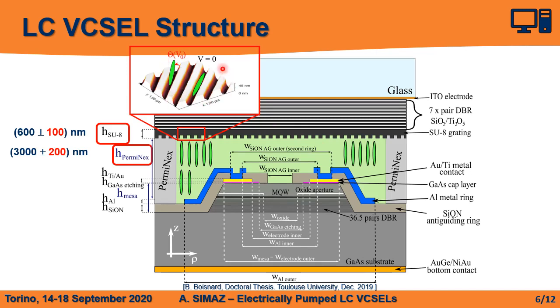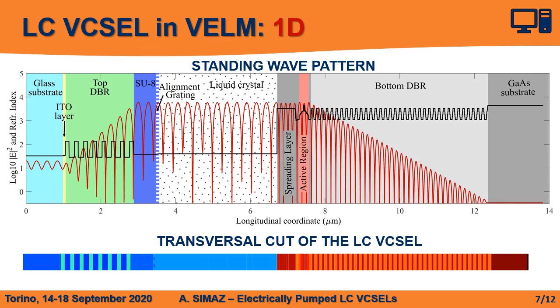At zero volts applied, the molecules realign themselves along the grating grooves, corresponding to the maximum value of the extraordinary refractive index. Applying a voltage, the molecules change their orientation and approach the ordinary refractive index value of 1.52. We should pay attention to the two organic material layers used to contain and fix the liquid crystal polarization, as they introduce large uncertainties in the optical path. For this reason, we exploit our optical solver VELM to study the one-dimensional optical features of our structure. Here is shown the transversal cut and the standing wave pattern. The liquid crystal pixel is assumed to be top-emitting.